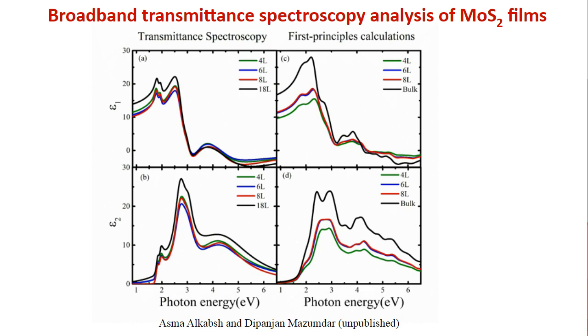Now, you can see there are lots of common features, and there are some differences too. But we think this is as good as it gets. Particularly, the dielectric constant values match up very well for different layers, right? And all the big features are captured, the C and the D. The AB exciton peaks are not captured in theory because this theory does not include those features, and I'm not going to detail why. You can see in theory you have a broad peak instead of this doublet structure. But the E transition is picked up. That means that E transitions are not excitons according to us.